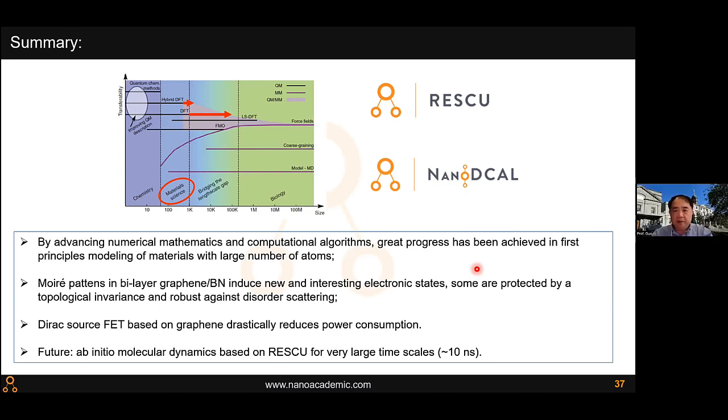Yes, definitely. We have some project to look at this line defect in graphene structures. They will scatter electrons across the interface. Because of this 5-7 defect, you can produce these lines which give you a grain boundary or something like that. So in this particular transistor work, and some other related work, in the physics and chemistry and engineering labs, they can produce very large scale, very nice single layer graphene, almost defect free. So these are for academic reasons. Yes, these defects we have to study.